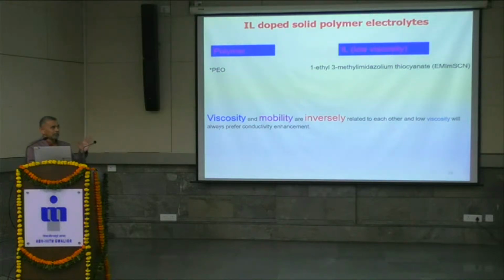So at that time I learned that if you go to ionic salts, meaning cation and anion, conductivity is going to increase. But for dopants like ionic liquid, I got a glimpse when I was doing my postdoctoral fellowship in South Korea. As a physicist, I know that viscosity and mobility are inversely proportional to each other. So my focus is always to purchase an ionic liquid which is hydrophobic, because I do not want any electrochemical reaction between the polymer and the electrode, meaning the dopant. And the other thing is lowest viscosity.